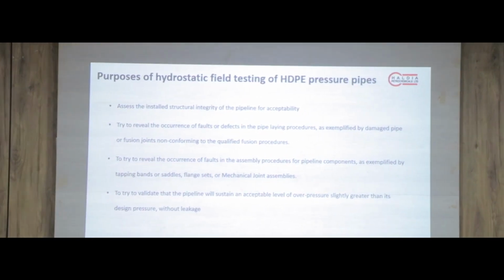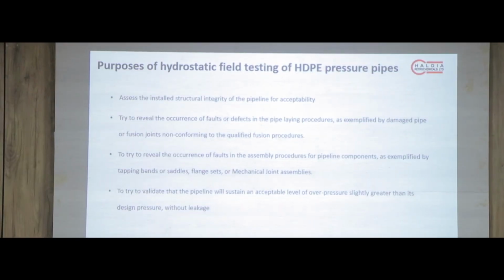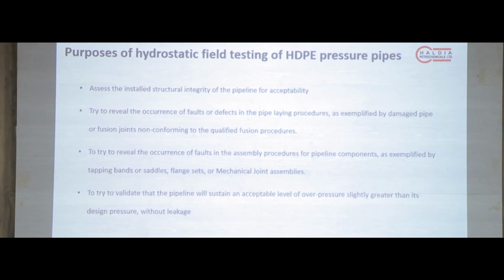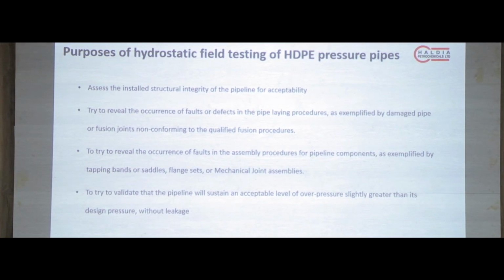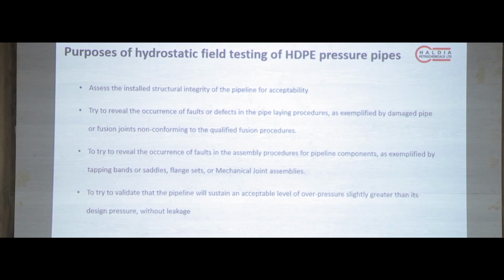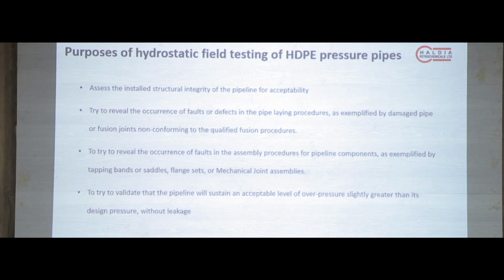What is the purpose of hydrostatic field testing? To assess the installed structural integrity of the pipeline. This is a very important point. It tries to reveal the occurrence of faults or defects in the pipe laying procedures, as exemplified by damaged pipe or fusion joints non-conforming to the qualified fusion procedures. Now, during the laying and jointing, if there is any minor fault, that may show up in the failure of the pipes, premature failure of the pipes.